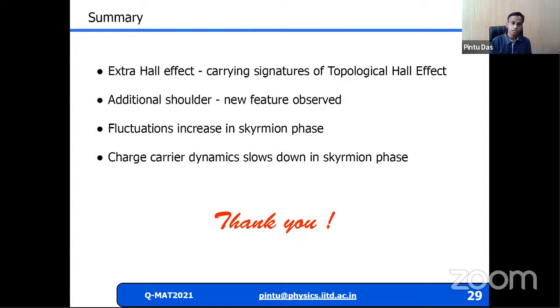We see that the fluctuations increase in the skyrmion phase, and that is very important both from theoretical as well as practical aspects, because in practical device applications the transport mechanism should be used to detect the skyrmions. For the first time we show that the carriers are actually slowing down in the skyrmion phase. So with this, I would like to thank you for your attention. I'm open for any questions.